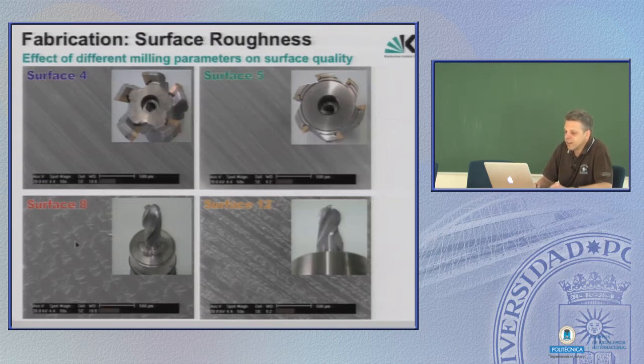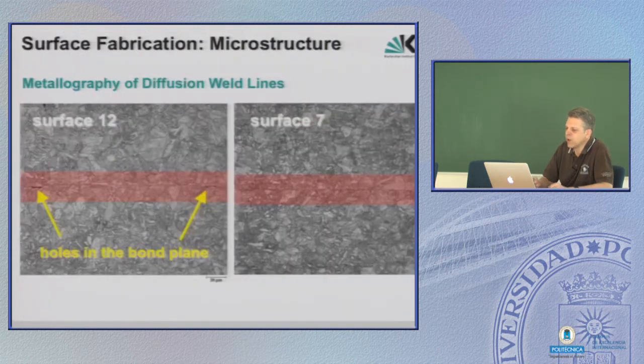And then we have seen that these surfaces, this red and that one, due to the chipping behavior of the Eurofer with these tools, produced some strange break-off effects during the fabrication. And if you look at the weld lines, that's a cut through the welded plates. Here is the weld line. Then in those cases where we had bad results, there have been some voids or holes in the surface, which is due to this chipping behavior with the specific tools we produce the surfaces.